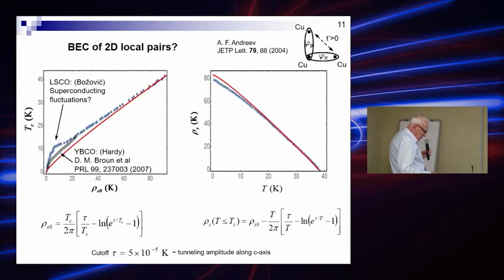Finally, we have fit this experimental curve. This second curve is old for YBCO. You see, it's much better given by Hardy, and the upper curve is given by Božović and his group, and this is probably superconducting fluctuation, this square root dependence here. But you see that this simplest formula fit excellent.